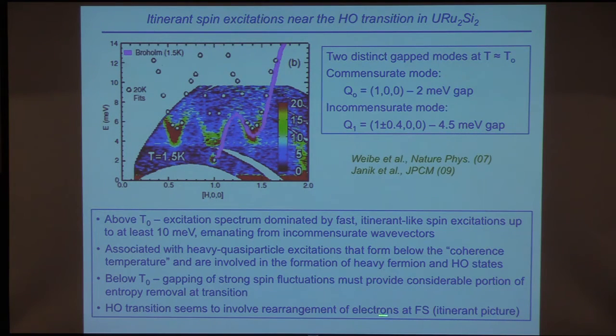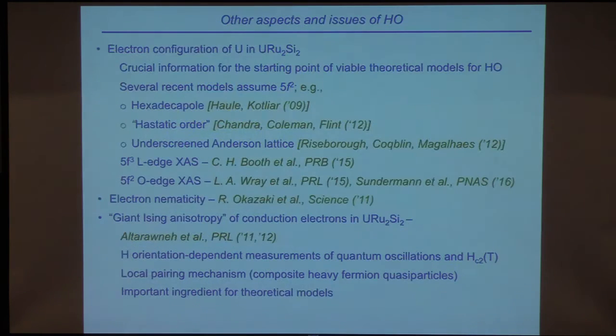And so, generally one has a picture where this hidden order transition seems to involve the rearrangement of electrons at the Fermi surface, which shows you that this has itinerant character in addition to this localized character. Okay, I'll just tell you a few other things. As I mentioned, there are some X-ray edge absorption measurements that have been made by Corwin Booth, where Corwin, I think, concludes this is a 5f3 configuration for uranium, and Andrew, I think, is proposing something closer to 5f2, although it may not be possible to say that it's purely one or the other, but it's very important for these various models that people are pursuing.